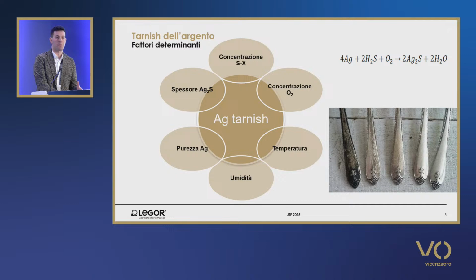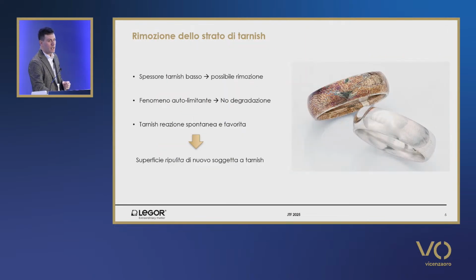And then certainly the purity of silver, because often silver objects are alloyed metals which have a greater reaction to sulfur compounds. So an impure silver object is more subject to tarnishing as compared to pure silver or galvanized silver. Well, the thickness is itself a barrier. And as a consequence, the greater the thickness of sulfur, the slower the reaction.